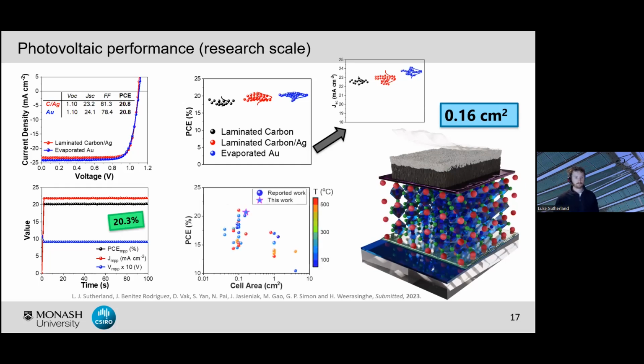And then once we compare to all the devices in the literature, so this is showing devices with carbon-based electrodes, so monolithic devices with carbon-based electrodes, we see that we're right up there on this research scale cell area. So around 0.1 centimeter squared, we're right up there with the best. And we could almost say we've achieved a record for low temperature fabricated devices if you look at that temperature bar over on the right-hand side there.